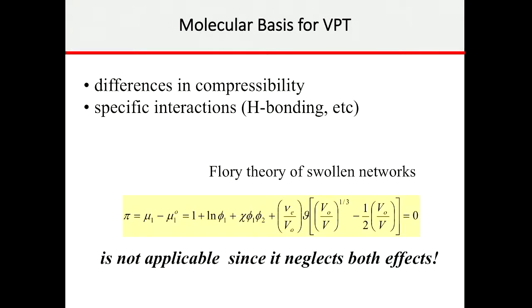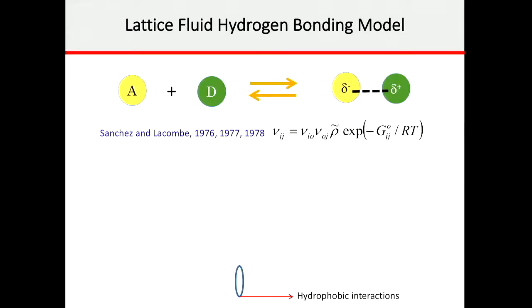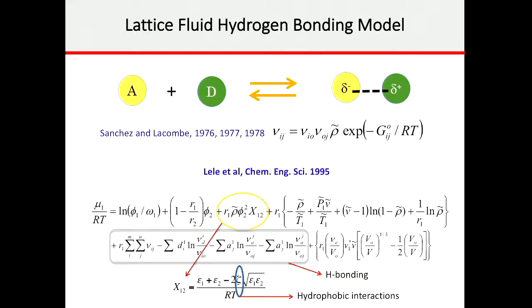To start with, the molecular basis for VPT. People were using the Flory theory of swollen networks. Tanaka, for example, used to modify this Flory equation, which was very famous, empirically. But the problem was that the differences in compressibility, the specific interactions, etc., were missing. So the molecular interactions were missing, and the lattice fluid hydrogen bonding model, which I wouldn't have time to get into in full detail, was something that we had to go to in order to incorporate the hydrogen bonding, the hydrophobic interactions, the entropic elasticity, and the rest of it, in order to give it a sound molecular basis.